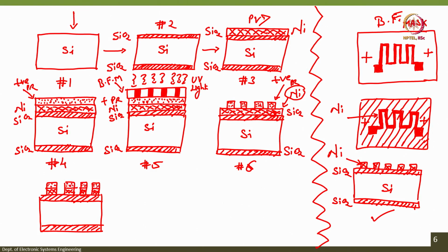The photoresist will remain intact. Nickel which is protected by the photoresist will be intact. Nickel which is exposed to the nickel etchant will get etched, right. You see, wherever there is photoresist, the nickel is still intact, right. Wherever there is photoresist, nickel is still intact.